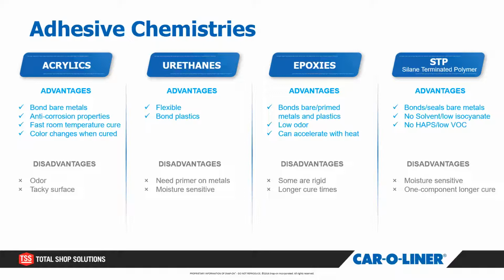We look at windshield urethanes, by far the most common. For the most part, urethanes are 1K. Windshield urethanes are moisture cure, but there are definitely 2K urethanes on the market, just not as common for what we see every day. And then finally, the STP adhesives. Again, these are typically seam sealers that fall under this category, but they bond or seal bare metal great. They have very low to no solvents, low isocyanates, and low VOCs as well.